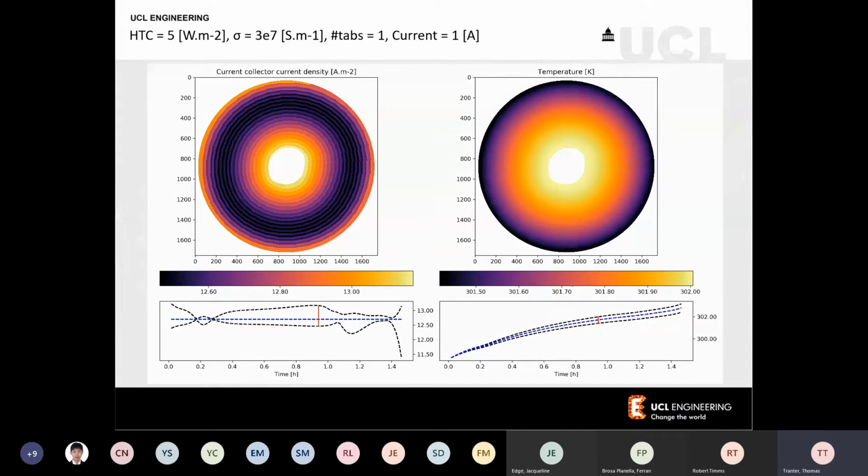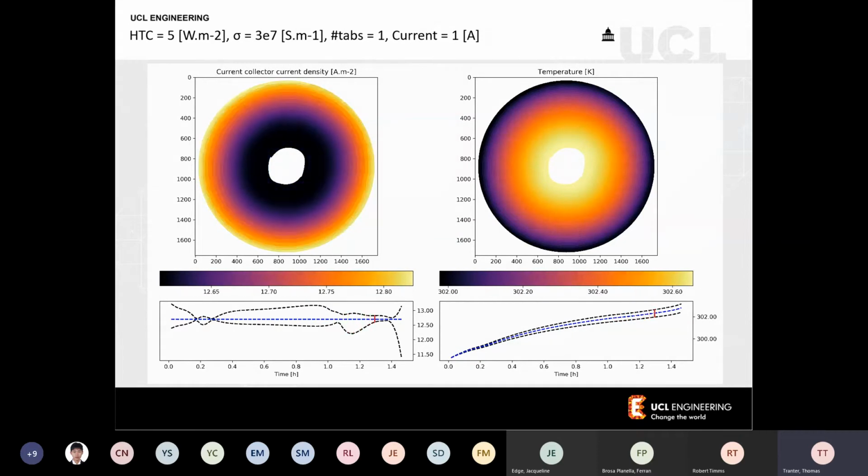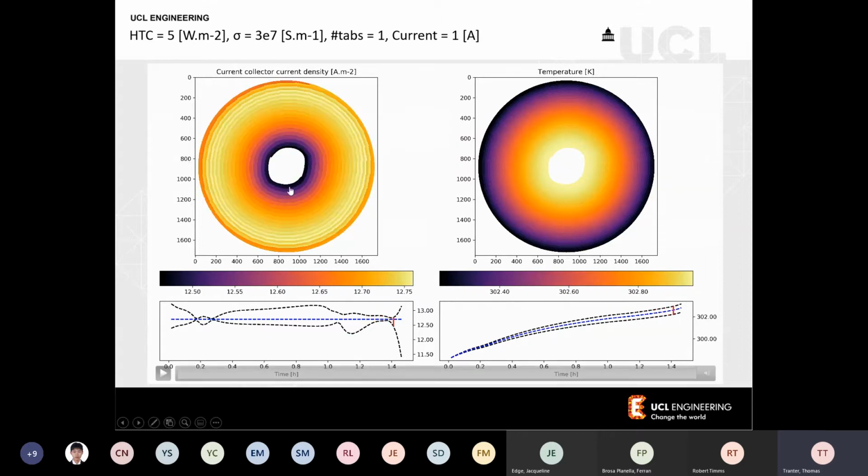That results in these heterogeneities in state of charge, which have an effect on the local resistance, and you get these interesting waves where certain sections of the battery have discharged more than others, and then their local resistance goes up, and suddenly it becomes less favorable to take charge out of those particular positions. So you get this wave-like nature, and that's mainly dependent on the shape of the OCV curve and also the tab placement defining this circuit resistance as well.